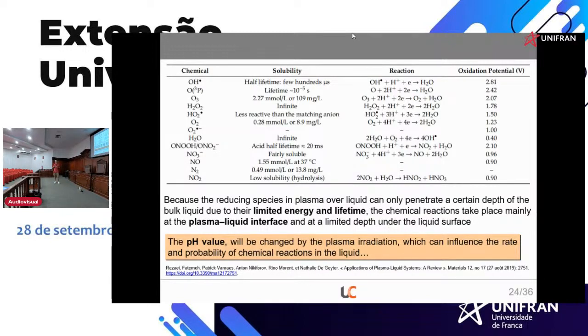The half-lives of these particles are very different. Some will live inside the liquid for an infinite time. So you will produce them, and they will stay in the beaker. They will stay inside the liquid, and others will disappear quite rapidly, like ozone. Because of the reducing species in plasma over liquid, it can only penetrate a certain depth of the bulk liquid due to the limited energy and lifetime. So mainly the reaction takes place at the plasma-liquid interface.